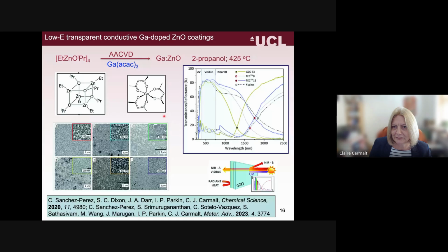So instead we designed this precursor, which is ethyl zinc isopropoxide, and it forms this tetramer shown here. We then dissolve this in propanol, and then we use gallium acac to add in dopant amounts of gallium to form our gallium doped zinc oxide. The SEM shown here is the plain zinc oxide, and then this is as we're increasing the amount of gallium dopant. And the best one was this one shown here, which had 3.8 atomic percent gallium doped into it. And it had a really excellent resistivity of 10 to the minus 4.